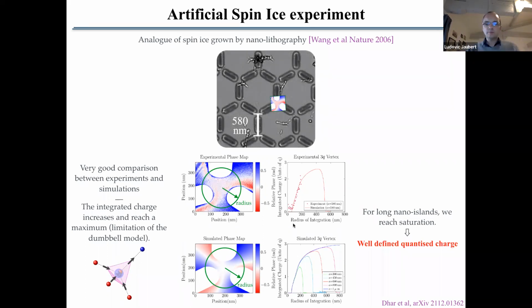So if I summarize, this is an artificial analog of a spin ice system. You can locally create Ising spins pointing either inwards or outwards. If you look at a given vertex and you have 3 spins pointing in, from the dumbbell model I was talking about before, these 3 spins pointing in will all have a positive magnetic charge at the head of these. And this positive magnetic charge will give rise to a singularity and to a specific phase map, where experiments and simulations compare very well to each other.